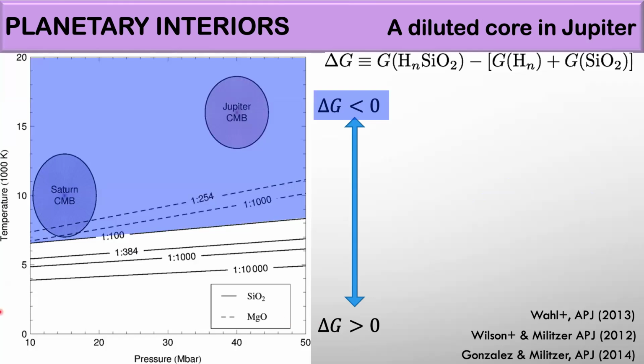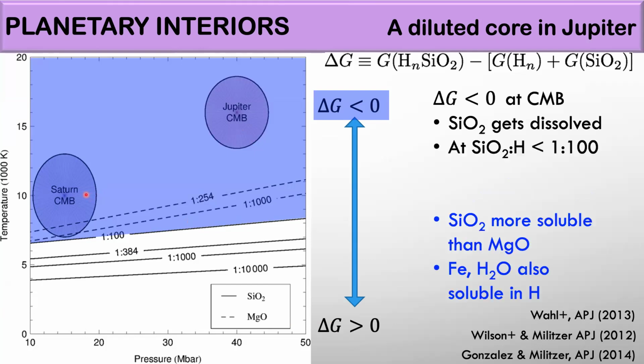So these temperatures and pressures that you see in this plot are all in the range where the Jupiter core mantle boundary conditions are and the Saturn core mantle conditions are. So it means that at the pressures and temperatures of the cores of these planets, the dissolution of this material, silica, is favored. And we did it not only with silica; in our group, all the members of our group have tried all the materials like magnesium oxide, iron, and water, and all these materials become dissolved by the metallic hydrogen. So it means that at the interior of Jupiter, metallic hydrogen is a pretty good solvent of rocks.